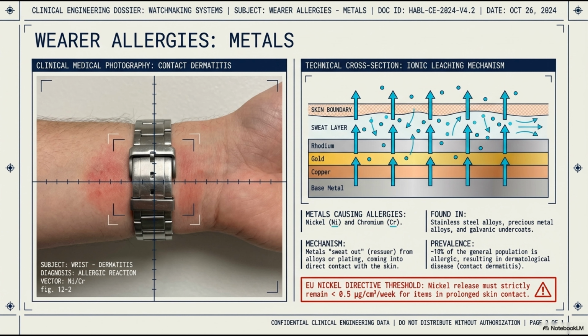This is why the EU nickel directive was enacted. Read the warning box at the bottom. It strictly mandates that nickel release must remain below 0.5 micrograms per square centimeter per week for any item in prolonged skin contact. If your bespoke stainless steel case fails this leaching test, it is illegal to sell in Europe. Period.